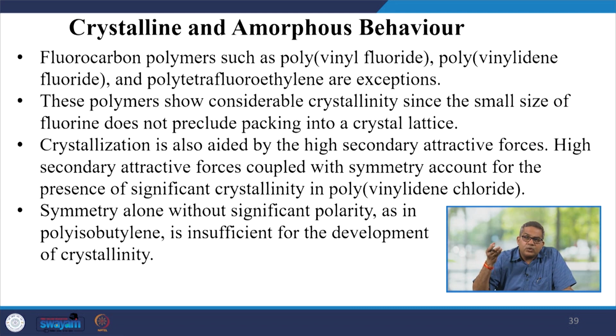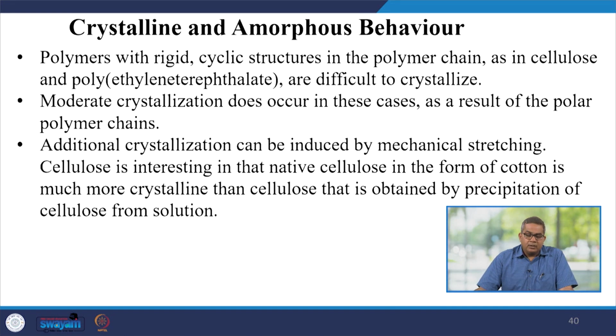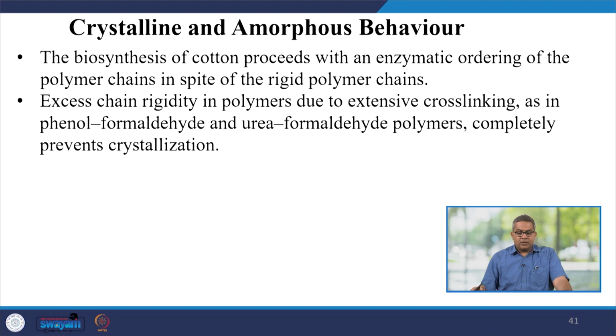Crystallization is also aided by a high degree of secondary attractive forces, coupled with symmetry, which accounts for the presence of significant crystallinity in polyvinylidene chloride. Symmetry alone, without significant polarity, as in polyisobutylene, is insufficient for the development of crystallinity. Polymers with rigid cyclic structures in the polymer chain, as in cellulose or polyethylene terephthalate, are difficult to crystallize. Moderate crystallization does occur in these cases as a result of their polar polymer chains. The biosynthesis of cotton proceeds with an enzymatic ordering of the polymer chain in spite of the rigid polymer chains.